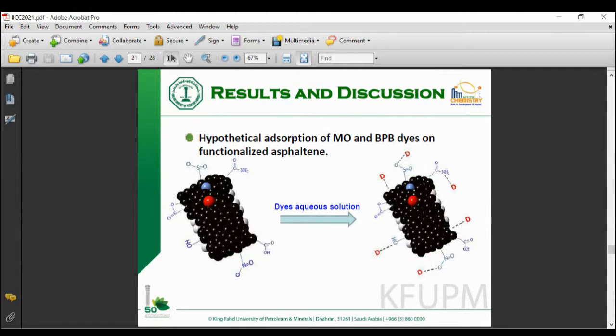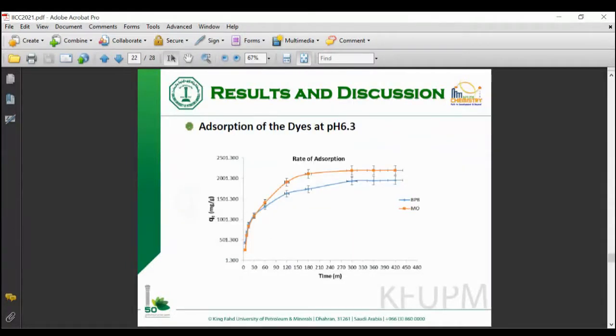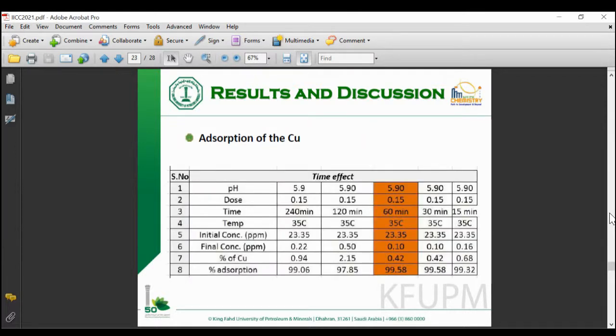And then when you use it for the dyes, more than 90%, 95% were adsorbed. So this is the one thing actually. You can see the adsorption here. When the pH is low, it helps for the adsorption of the metals. Actually, this is close to neutral, so it's good for the dyes. I'm just showing one slide here for copper, and you can see that we used different parameters: pH, dose, time, temperature, concentration, and percent copper, percent adsorption. You can see 99.58% of the copper metals were adsorbed in 1 hour.